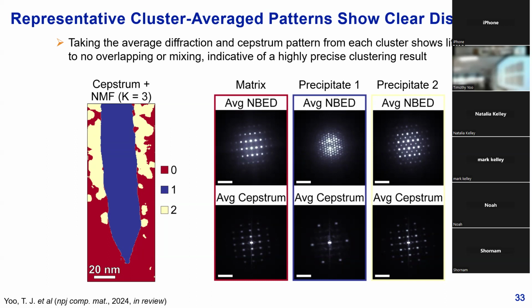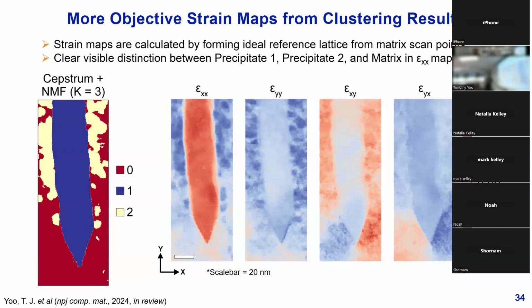And so, of course, going back to the original motivation for this task, first, there's actually a caveat here. So this result is actually really good for forming more objective strain maps. Generally when you're doing strain mapping, you have to build some kind of reference region to compare all the values to. And so this is a largely subjective step. In some cases, it might be pretty easy to pick out a pristine region, but again, it's largely subjective.